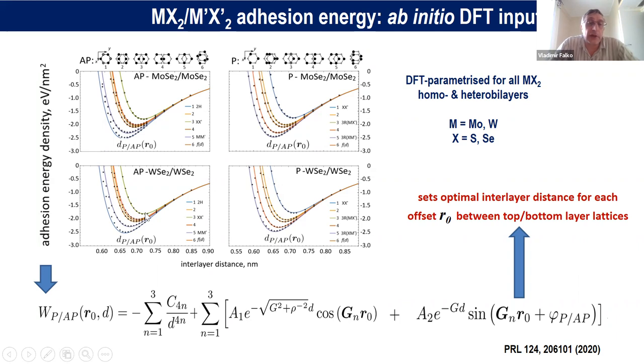Then the highest energy corresponds to the case when the two chalcogens are on top of each other. We call it XX' stacking, so that a chalcogen in the top layer appears to be on top of a chalcogen in the bottom layer. There is similar behavior in terms of XX stacking for the bilayers with parallel orientation of the unit cells. But for the lowest energy, we actually have two degenerate configurations, two configurations with the same energy. They are mirror images of each other. They're basically the twins of each other. And they correspond to that in the bottom layer, a chalcogen appears to be under the metal in the top layer, whereas the other sublattices in each layer appear in the middle of the hexagon in the layer above or below. And there are two configurations that you can get, one from the other by mirror reflection. They have the same energy.